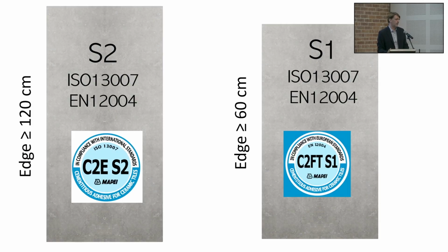or S2 adhesive. Every country has more or less its regulation. We give this kind of indication. So higher than 120, we go with S2 adhesive, maximum deformability for the adhesive. Higher than 60, we go with deformable adhesive. So when you provide advice to our customer, we can say, no matter what brand you will use, but in this job site, I need you to respect the standard for the adhesive for this kind of application. Otherwise, we may have some problem on the final application.